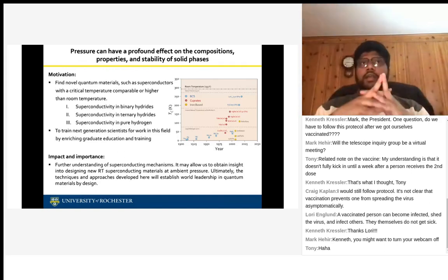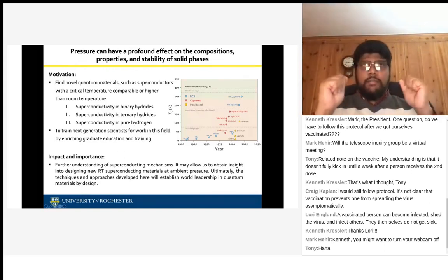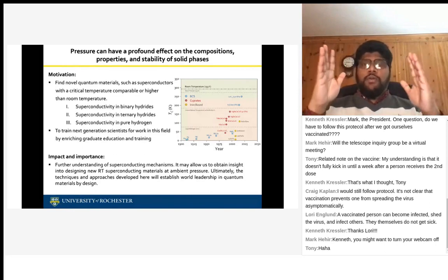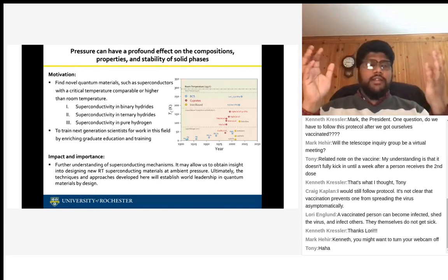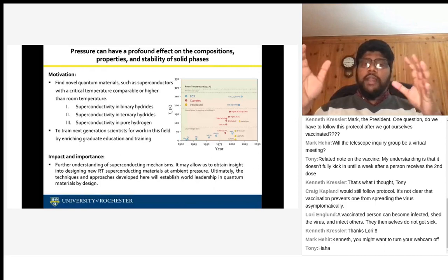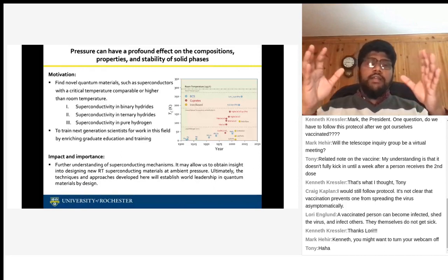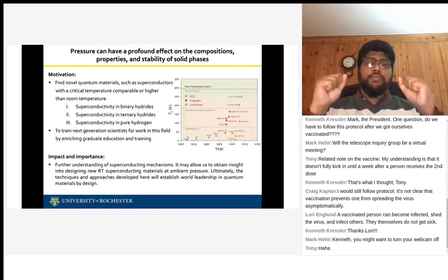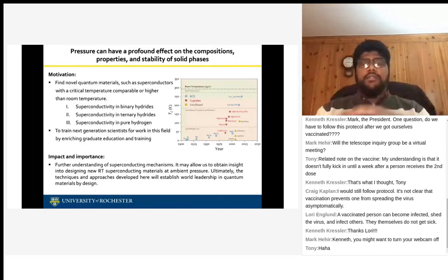Just to give a background, hydrogen, even though it's a gas at ambient conditions, if you go to higher pressure, just like in the interior of Jupiter, becomes a metallic state. And theoretical calculations show that metallic hydrogen can be a room temperature superconductor. The simple recipe for a superconductor is lighter elements, stronger bonds. Hydrogen easily has both criteria, so it can be used as a favorable case for a superconducting material.